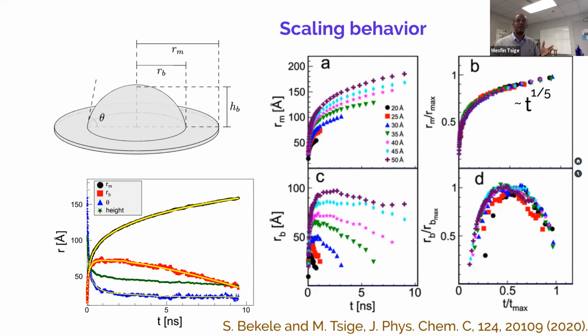It may have to do with the fact that we are taking molecular level information of what's happening, taking actual water molecules. And encouragingly, recent experimental results showed a similar behavior. The experiments found t to the power of 1/4 for the spreading of a water droplet on a textured surface. So their surface is slightly different. Yes, it is hydrophilic, completely wetting the surface, but slightly textured compared to our atomically flat surface. They found even much faster dynamics than what was predicted by Tanner's law. The details of this recent work can be found in our recent publication.